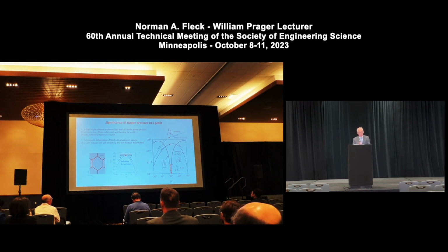And consequently, the plant cell switches from behaving in an open cell manner to one of being a constant volume mode of deformation, which takes you from this dotted line, which is the empty mode where volume can change, to the black line. Notice the difference in normalization. This is rho bar cubed, so this is actually a very low modulus, whereas the black line is normalized by rho bar, the relative density, and so the response is much different. So constant volume constraint has a major impact upon response.